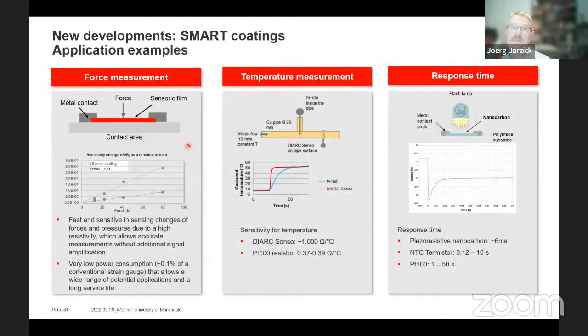So here are some examples of this. For example, for the force measurement, we had a contact area where force can be applied, and we have the sensoric element here. These are the connectors. And if I now compare the response of this sensoric film to a classical sensor, you see that, first of all, it's very linear with respect to the force, which is here on the x-axis, but also that it is more sensitive than the classical sensor. So it allows you to very sensitively detect these changes in force.